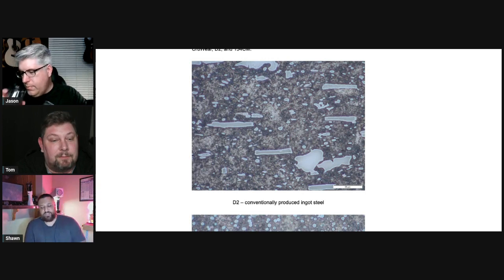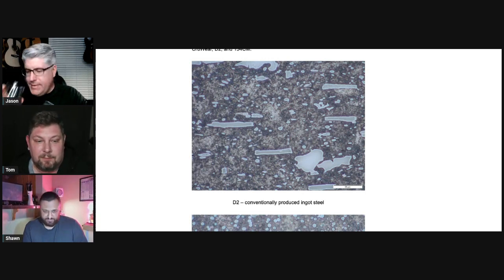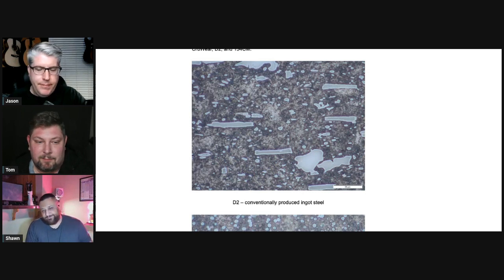There's no measurement for edge aggression currently. There's testing that's being done right now to figure that out. But the D2 that's not CPM, it's significantly larger in size. So when we're looking at that as a layperson, we should be able to see these white blobs are really big. We look at the scale bar in the bottom right. We look at these big blobs, and we can know as a fact this material is going to have more wear resistance, but it's not going to have as much toughness.